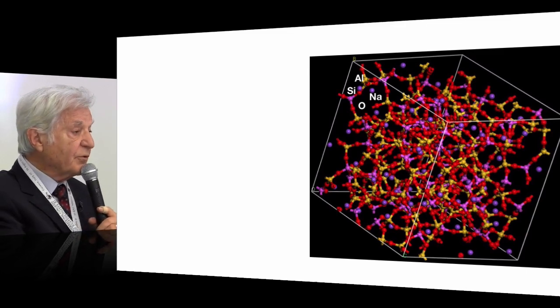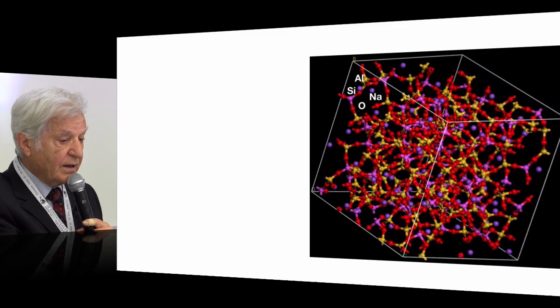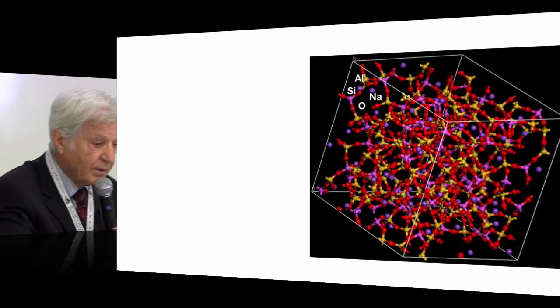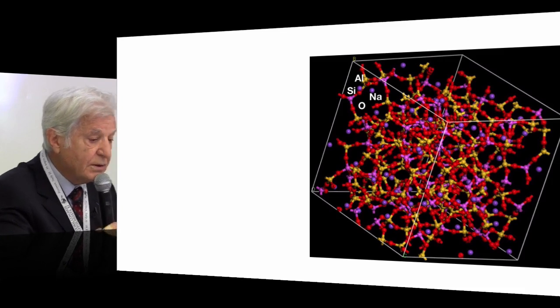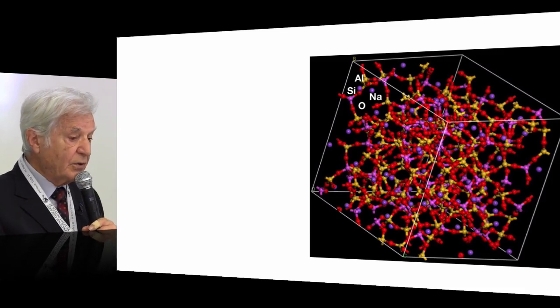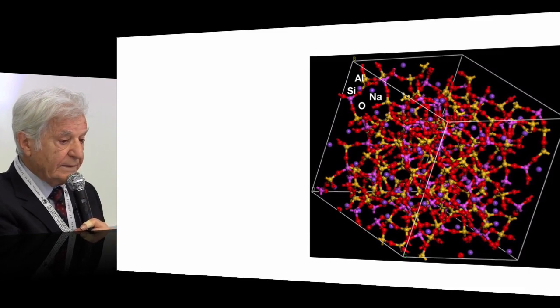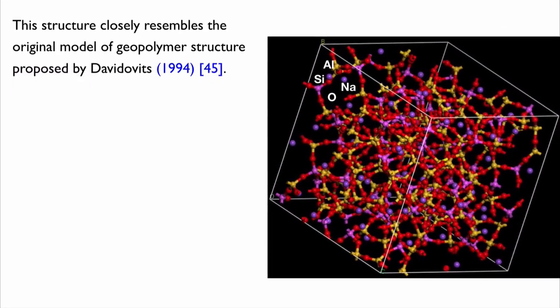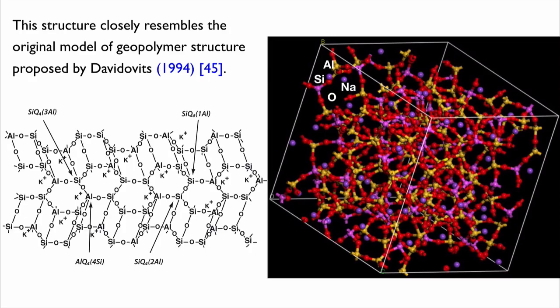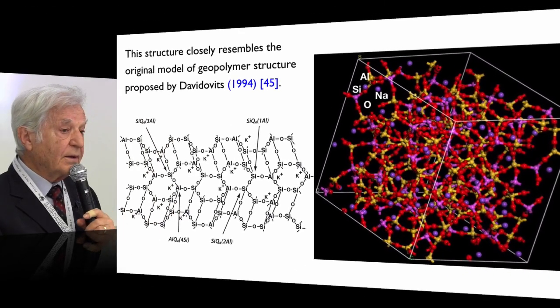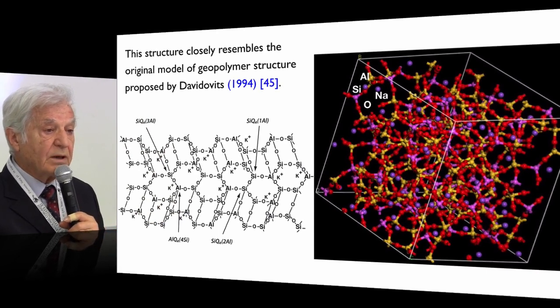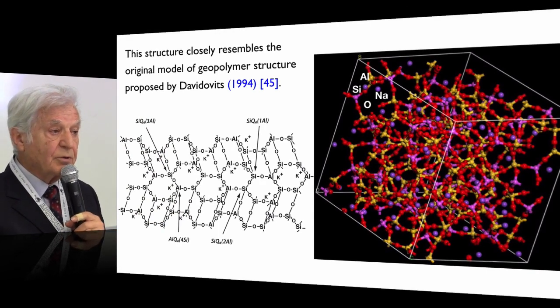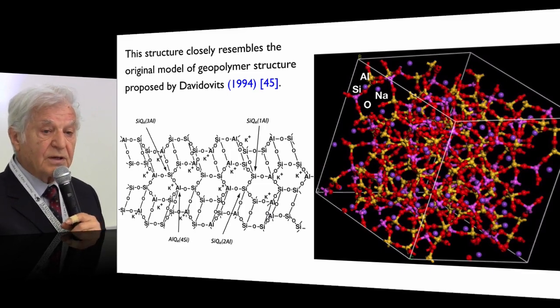And they proposed this type of three-dimensional polymeric structure. So you have the Si in light purple, you have the oxygen in red, the aluminum in yellow, and the cations in blue. And they claim and write, well, this structure closely resembles the original model of geopolymer structure that I proposed 24 years ago. So we didn't have these computers, but we were able to propose it. Today, everything should be proposed by the computer, otherwise it is not science. But we used our brain in order to really understand what we were doing.